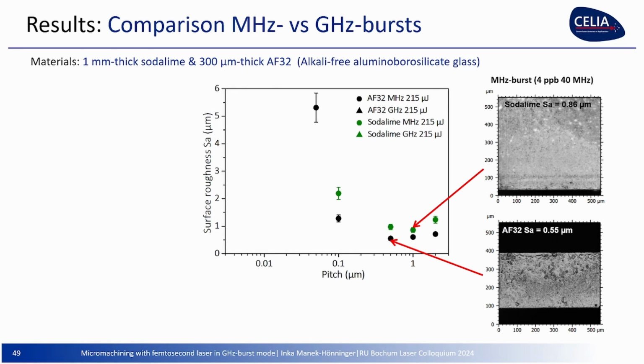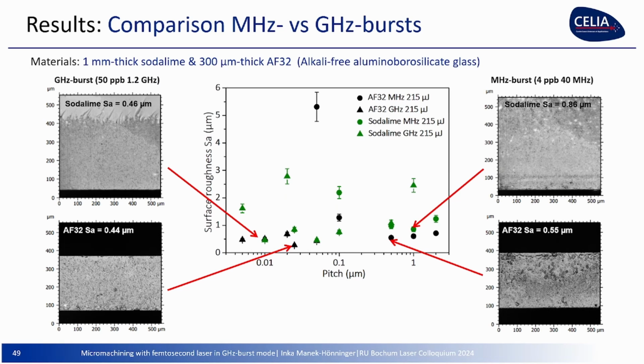So the results, we wanted to do a fair comparison between megahertz and gigahertz. So we kept all the parameters constant, except that with 4 pulses at 40 megahertz, where we got these results, and 50 pulses within a 1.2 gigahertz burst. And what you can see, well, the results are slightly, the surface roughness is slightly lower, it should be as low as possible to be good, slightly lower than for the megahertz burst.